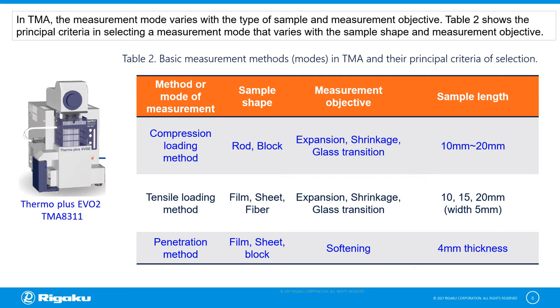The tensile loading method is used for the measurement of fiber, sheet, or film type materials for the detection of expansion, shrinkage, or glass transition. The sample length here is specific: 10 mm, 15 mm, and 20 mm in length. On the other hand, the penetration method is used for the detection of softening temperature in film or even block type samples. The material thickness is 4 mm in size.